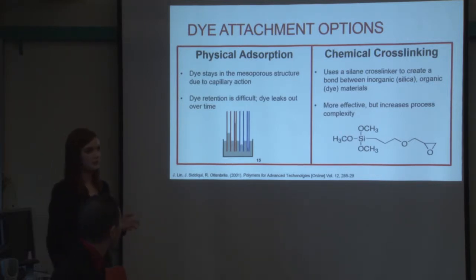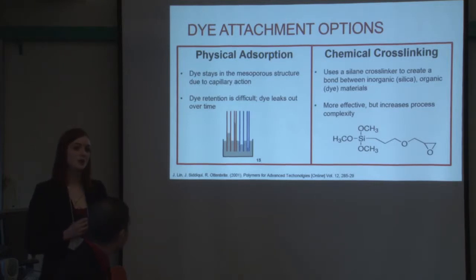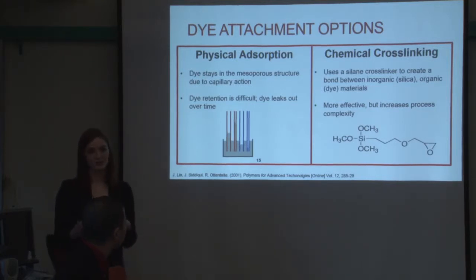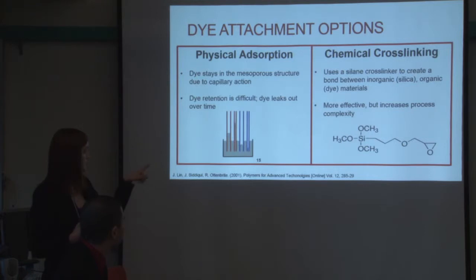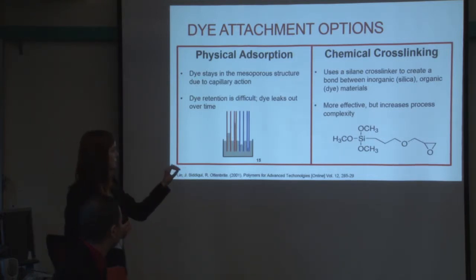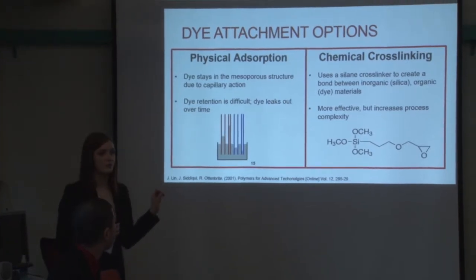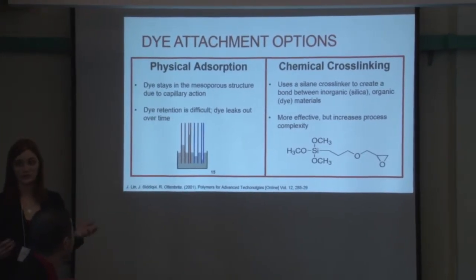So this isn't very good if you're trying to create a long-lasting hair dye. So a decision that we made was to try using a chemical crosslinker instead. We used something called a silane crosslinker, and the image there is of glymo, which is what we used. It basically can make a chemical bond between the inorganic phase, which is the silica precursors, and the organic phase, which is the dye.